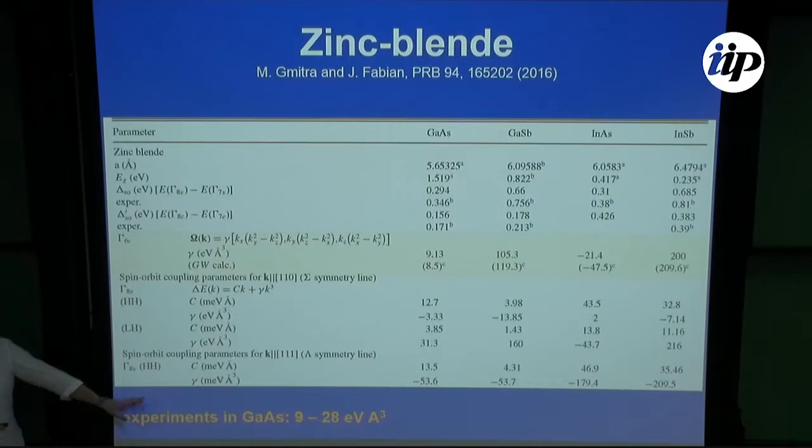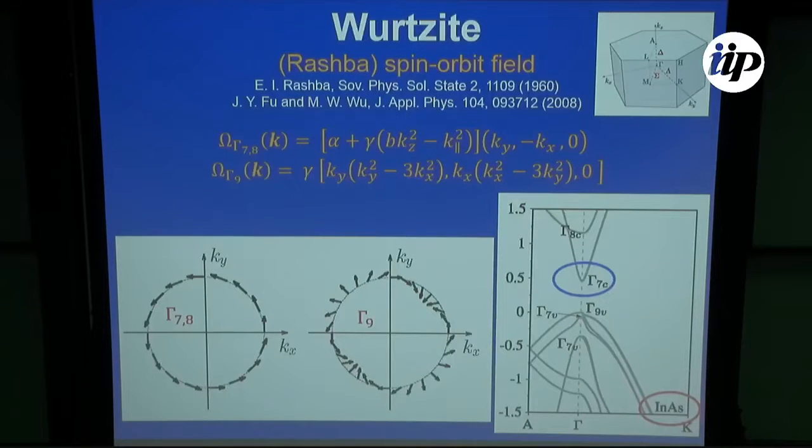Lately going towards 9, like GW, because in the literature, people take the simple model, make a complicated experiment on a complicated system, and fit the simple model. So this value of gamma in experiments is to be considered as a fitting parameter, not a real description of a band. Let's say you have 5 subbands and so on. Your numbers will be different. So this was encouraging, and then we went to wurtzite, because in wurtzite, as I said, no calculations like that, nothing much is known. So this has to be taken as a prediction.